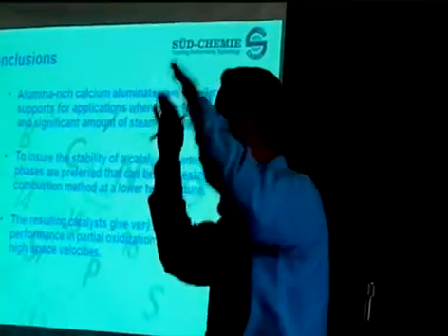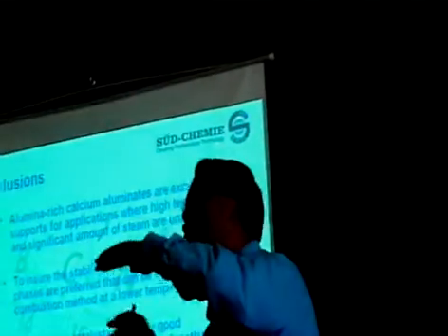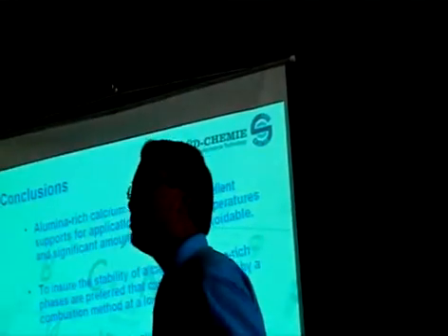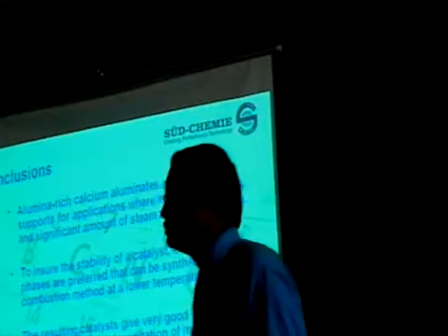When you put it downstream and you have water or oxygen, the material has to be reduced and it is really hard to stay in the reduced form. A lot of the time they have to put in some kind of noble metal to reduce the first layer, and then get enough hydrogen pressure to reduce the nickel.